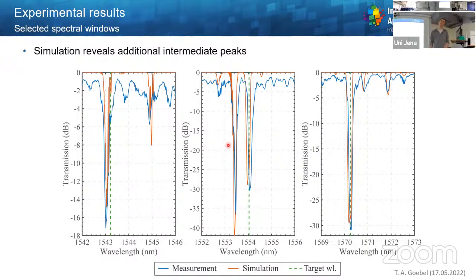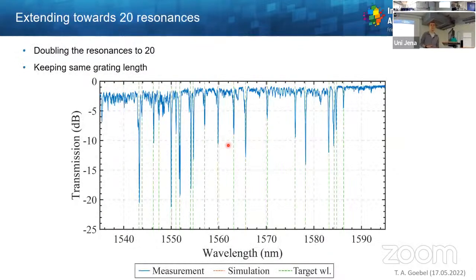As I've shown before, we had a grating with 50 millimeter length and 10 resonances. Just to demonstrate that this is very nicely scalable, we doubled the resonances to 20, keeping the length the same. Of course, then we need to increase the amount of refractive index change we need to induce. And this leads to weaker resonances because we are already in the saturation regime of our material. But nevertheless, you can see that we could address all 20 resonances.